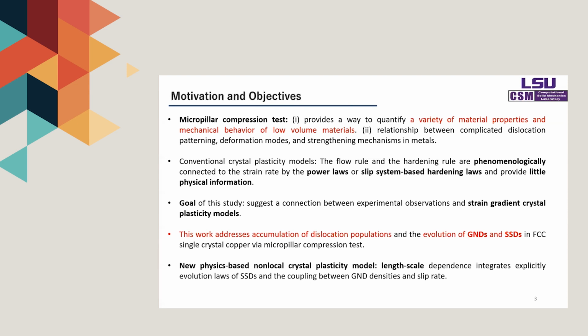To do this, a crystal plasticity model accommodates various dislocation mechanisms. In this study, we address the evolution of geometrically necessary dislocations and statistically stored dislocations in face centered cubic single crystal copper via a micropillar compression test.